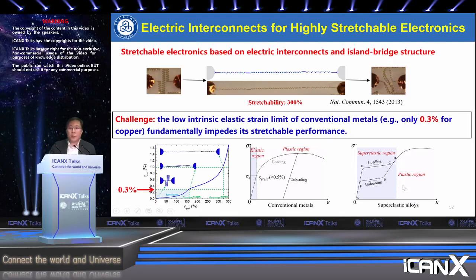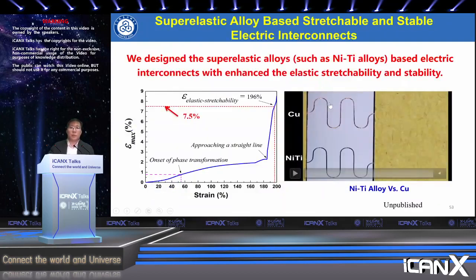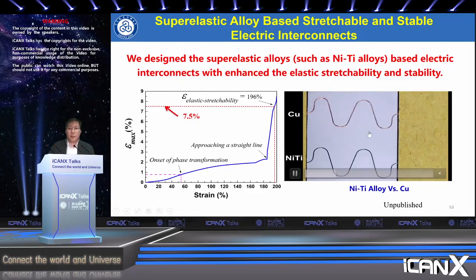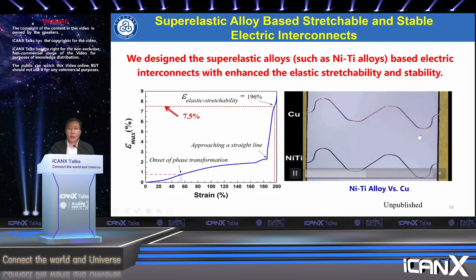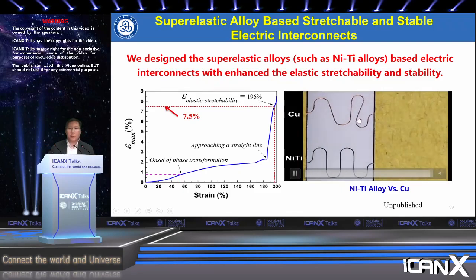And we know that shape memory alloys have superelastic properties with an extended percentage, which can potentially be used as a stable and stretchable electrical interconnect. So in this work, we designed superelastic alloys such as nickel-titanium alloy based elastic interconnects. Here you can see it has about 7.5% superelastic properties, and we can have enhanced elastic stretchability and stability. Here you can see the comparison of the nickel-titanium alloy with copper nanowires with serpentine structures. When it comes back to the original state, the copper electrode already has a shape change, but the nickel-titanium structures have a totally reversible process.